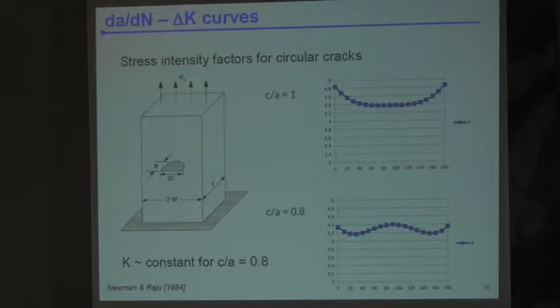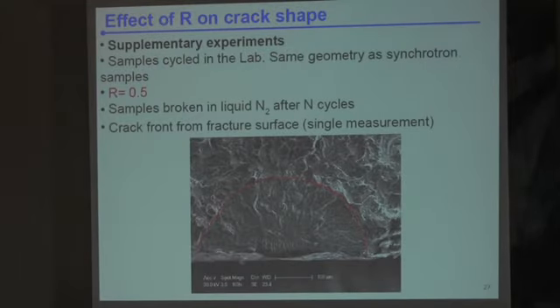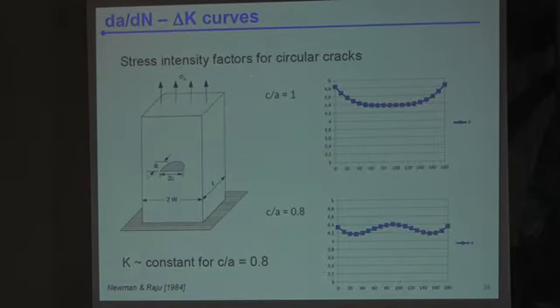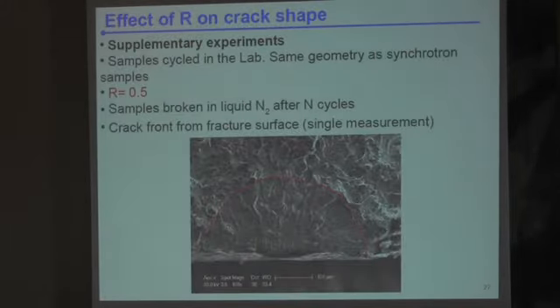And this is supposed to be the equilibrium shape for a crack, where you grow your crack front at more or less balanced values of the stress intensity factor all along the crack front, right? But in that case it was puzzling, because we had an out of equilibrium shape for most materials. Only material number 4 was showing something like this. So what Pablo did,